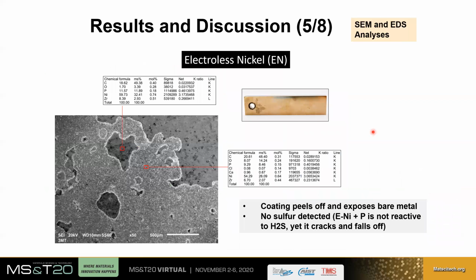All right, let's move on to a second coating. Here I'm showing you electroless nickel. So we do see some spalling, delamination. We definitely have at least 2 layers. The composition of these layers are shown here. Even though there is some reaction with sulfur, we are not truly able to detect it very carefully. However, we see flaking off. Okay.